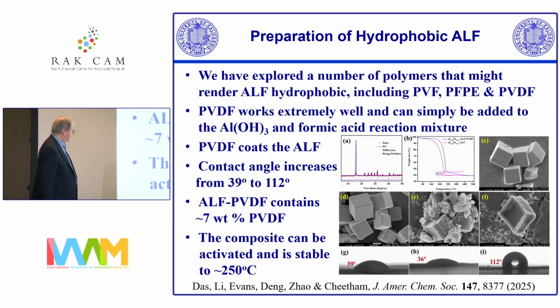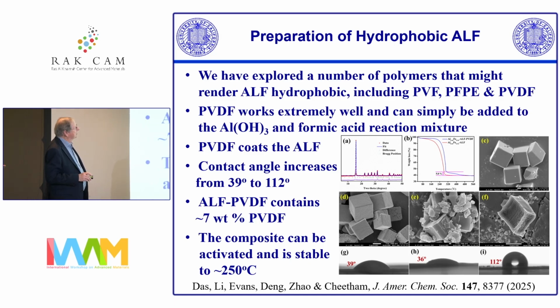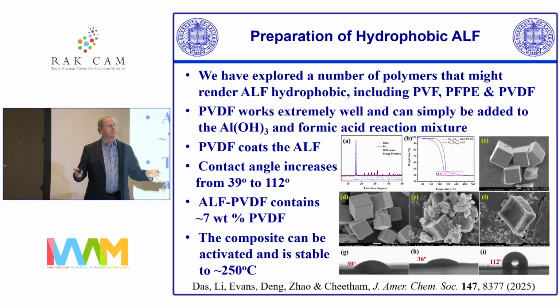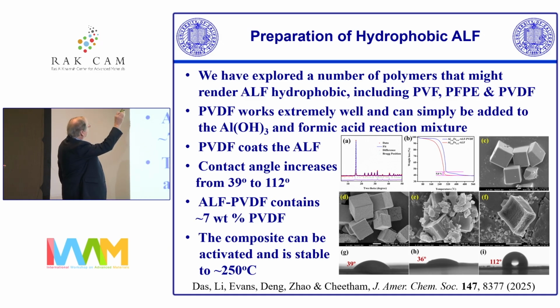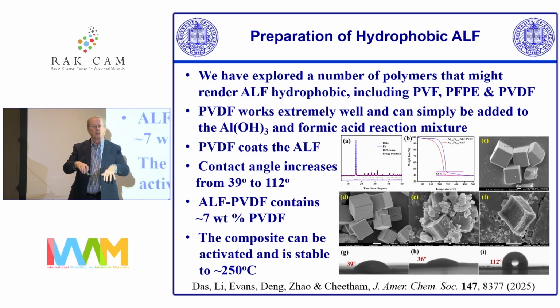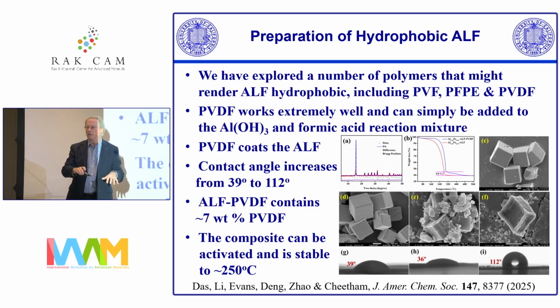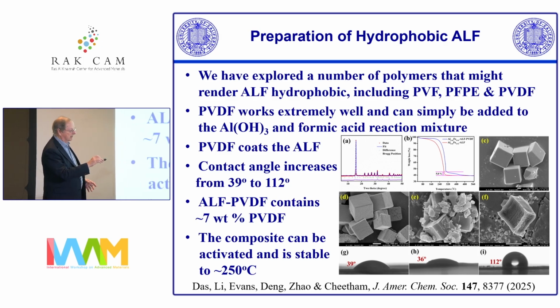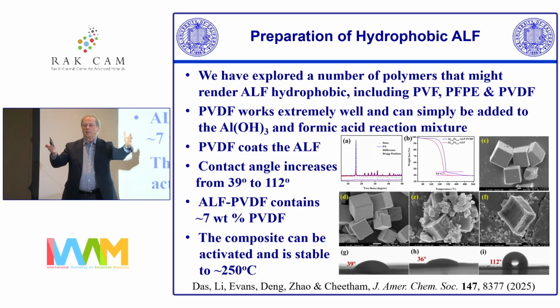So one of the things that Rajesh Das did, who's a postdoc who worked with me in Singapore, he's just about to finish in Singapore, was to explore the possibility of making it hydrophobic. And we explored a variety of polymers, fluoropolymers, and the one that worked really well is PVDF, polyvinylidene fluoride, and all you have to do is put the PVDF into the reaction mixture with the formic acid and the aluminum hydroxide. You don't need any other solvent because formic acid's a liquid, so it acts as a solvent as well as the reactant. And by a mechanism that we don't understand, when you do that, the material still crystallizes out with the PVDF on the surface.